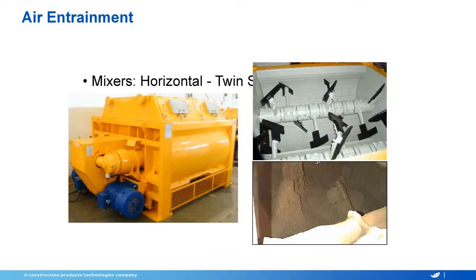For example, it would typically take more air entraining agent in a pan mixer to get the air you need than it would in a twin shaft mixer or a drum mixer, just because the mixing action is different. So if you change mixers, be prepared to do some testing with the air. If you get a new mixer, get a new liner, or install new blades, any of those things are going to impact the air. If you have buildup on the mixer, worn blades, or gaps between the blades and the body of the mixer, all those things are going to play a huge role in how much air you get and how long it takes to get there.